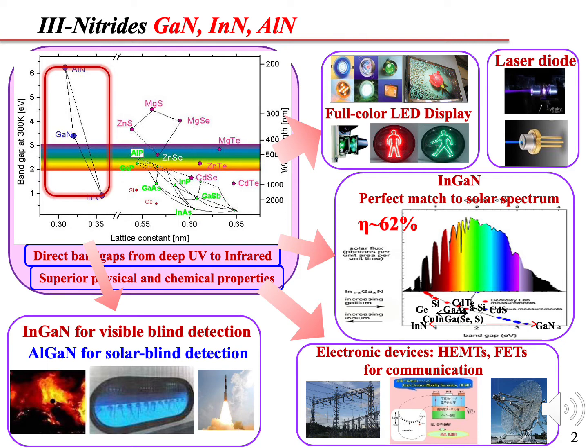Another important application is the solar cell. You can see that for indium gallium nitride, the energy band gap has a nearly perfect match to the solar spectrum. So compared to other material systems utilized for solar cells, theoretically indium gallium nitride can achieve a very high conversion efficiency if we take full advantage of the InGaN material.